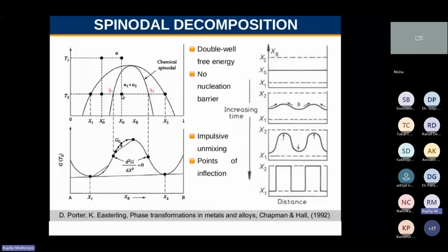So the alpha will decompose into alpha 1 plus alpha 2 phases, right? And this happens without nucleation and happens spontaneously, because if you see the corresponding Gibbs free energy diagram at temperature T2, you will see if you choose a composition inside the spinodal line, then a small fluctuation in composition basically decreases the Gibbs free energy, right? And that is why even a small thermal fluctuation causes a phase separation.